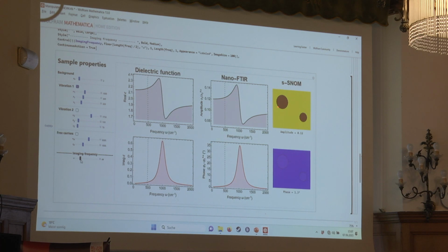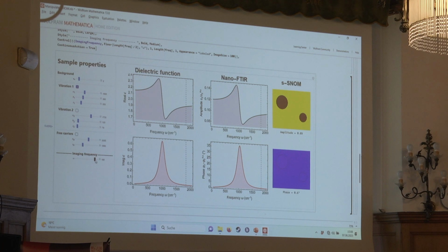And we have here a biological sample, an organic sample, where the refractive index is normally quite low, and that's why it's appearing dark. And it doesn't matter, or rarely matters, which frequency we use. The amplitude image is always the same. Yeah, so if we look on this scale, we don't learn something from the amplitude. But I've shown before, if you zoom in and you really quantify, you do see a difference.